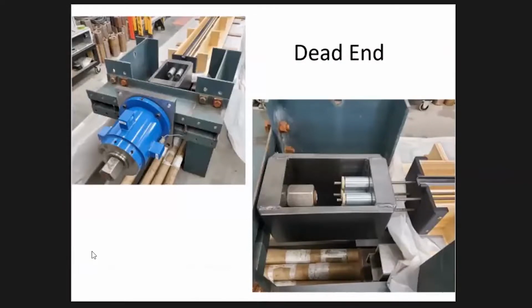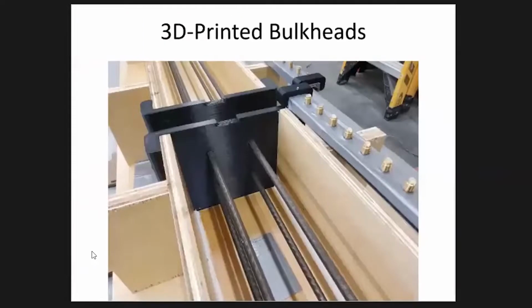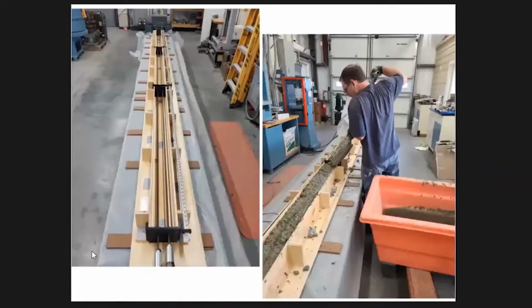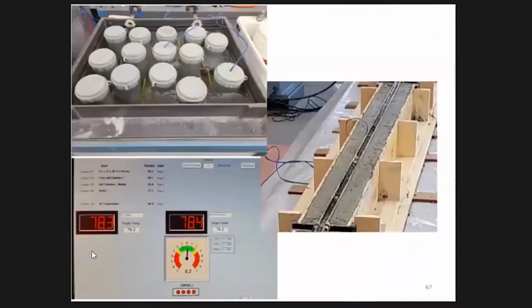So we have a check and balance between live and dead end. To get the exact edge distances we wanted, we 3D printed the bulkheads. We found that's the best way when we want to get tight tolerances. If you stand in front of a drill press, it's a little bit harder, but we just 3D print the bulkheads. The picture of Jason filling the forms is after we tension the wire and batch the concrete.